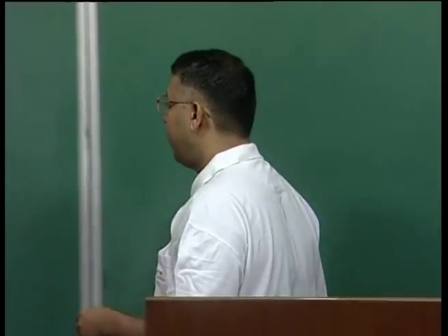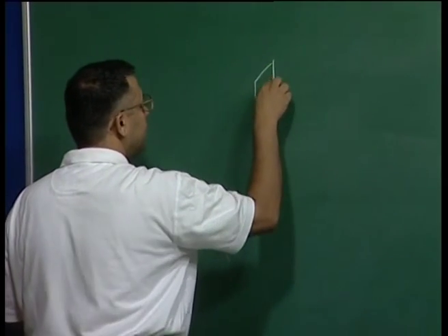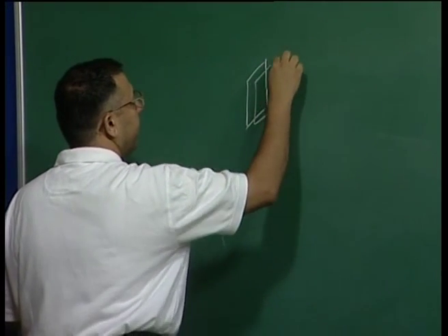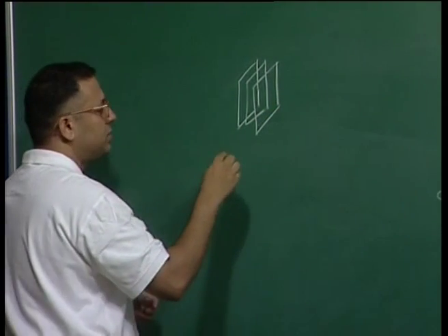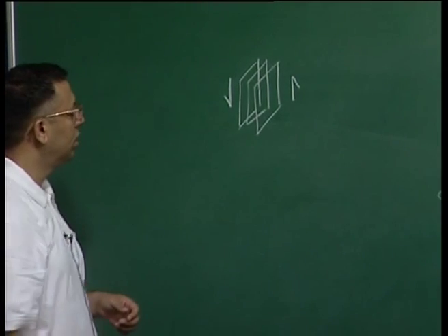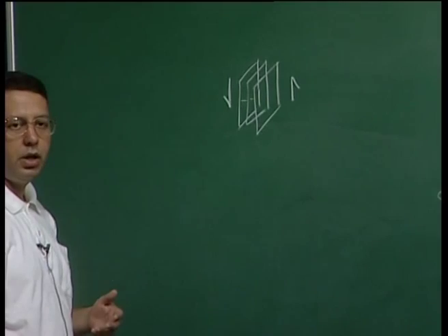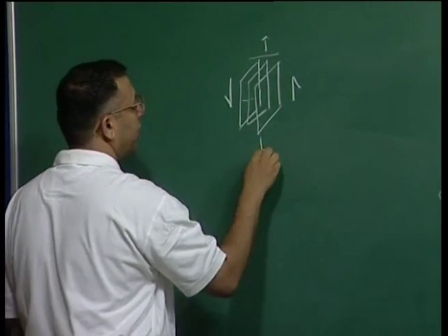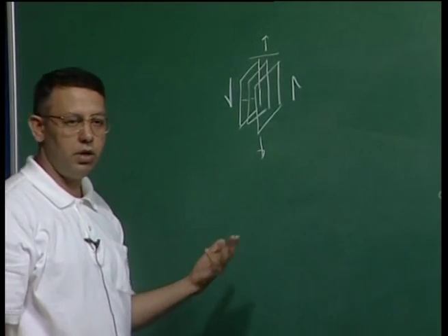But suppose now I pull along the planes, that means now I have two options. Now I have my graphene planes here. I am not drawing them like hexagons, but these are my planes of graphene which form the crystal. Suppose I am shearing my planes like this, my shear is in this direction, then the van der Waals bond between the planes is going to be sheared, and this crystal is going to be extremely weak. On the other hand, suppose I pull along these two planes, the graphite planes, then actually I will be stretching the carbon-carbon covalent bond, in which case the crystal will be strong.